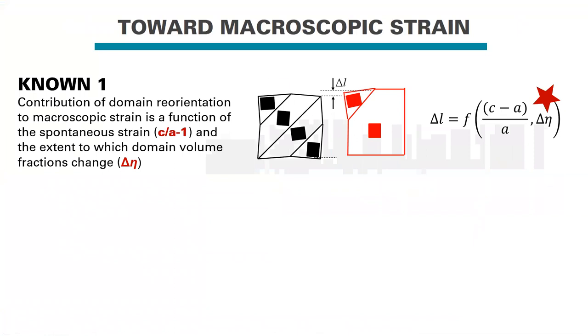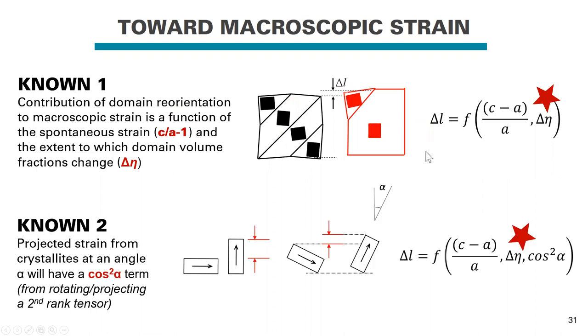So let's connect this microscopic phenomena with macroscopic strain. So there are two things to note. The contribution of domain reorientation to macroscopic strain must be a function of the lattice aspect ratio, or the spontaneous strain, and it must be a function of the extent of domain switching. And so generally, this is the type of function we might expect. But in a polycrystalline material, we have other orientations, and so we need to account for their contributions to the macroscopic strain. And those of you that are familiar with tensors would appreciate that if you rotate or project a second rank tensor, there's a cosine squared term. And so this cosine squared term allows you to project the strain into the vertical direction. And so now we appreciate that this delta L of a polycrystalline sample is a function of the spontaneous strain, the degree of domain switching, and cosine squared alpha.